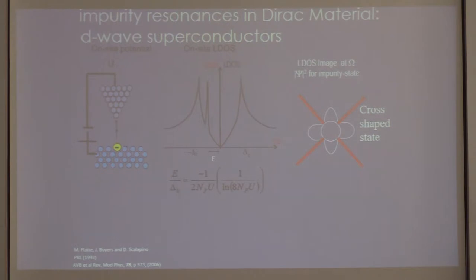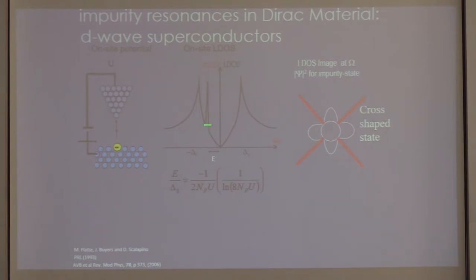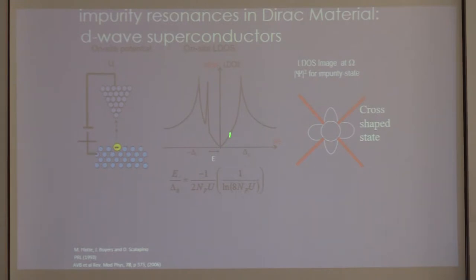Let's take one defect and place it inside this D-wave superconductor. It's known that impurities suppress superconductivity, but with only one impurity, the damage should be done locally — no global suppression. If I have one impurity per cubic centimeter, the damage is only local. What you see locally is a resonance that moves inside from the continuum and starts populating the gap — a precursor of gap filling and ultimate collapse of the superconducting state. This is a version of the Yu-Shiba-Rusinov state in the D-wave superconductor.